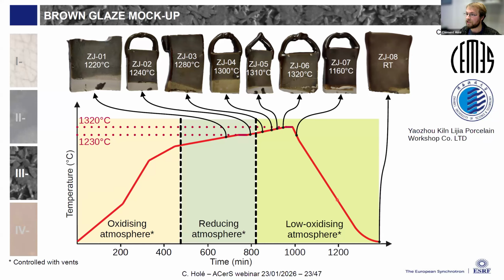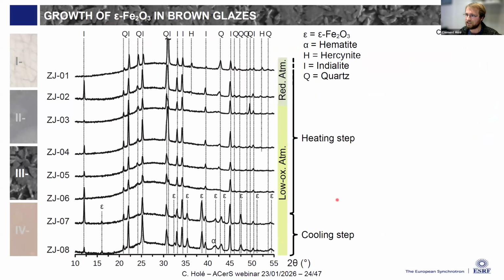So the first tool I used to characterize this series was X-ray diffraction. And from what I could see, epsilon actually appears only on samples 7 and 8, which correspond to only the two samples that were extracted from the kiln during the cooling step. And in the previous heating step, we have no trace at all of iron epsilon oxide.